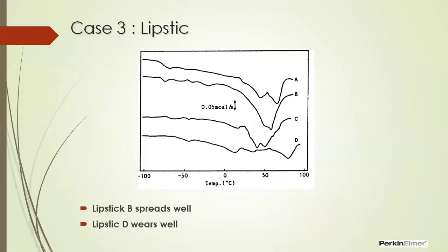Lipstick, the interesting point: not only the polymer industry, but the lipstick and cosmetic industry also uses DSC as a tool to evaluate their properties. Here there are 4 lipsticks. Usually women like to hold their lipsticks from 9 to 5. So if you see the DSC, let's concentrate on the B curve, which starts melting at around room temperature, having a comparatively broad, but I will still say narrow, melting up to 70 degrees centigrade.